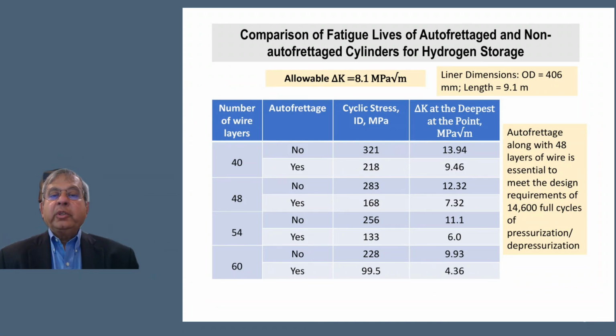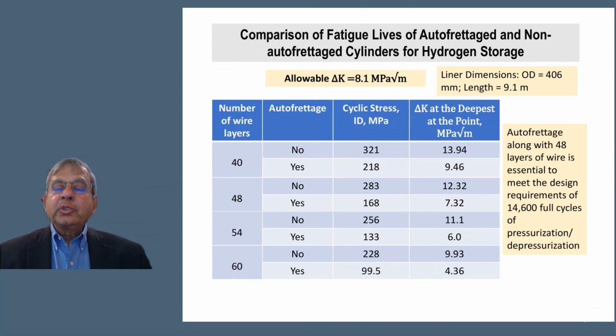Now I'm going to go directly to the life of the vessels. If we make comparisons of fatigue lives of autofrettaged and non-autofrettaged cylinders for hydrogen storage, we get the following results. But let me back up a little bit and talk about autofrettage and non-autofrettage. Non-autofrettaged cylinders are not subject to the very high autofrettage pressures during which the liner goes through plastic deformation. Still, there are compressive stresses from the wire tension during the wiring process. So even a non-autofrettaged cylinder does experience some compressive stresses at zero pressure, and those compressive stresses have to be overcome by the service pressure before it goes into a tensile range.